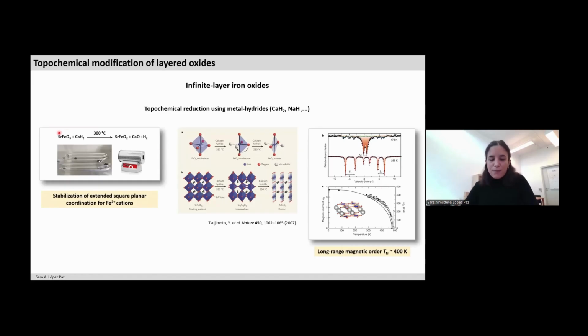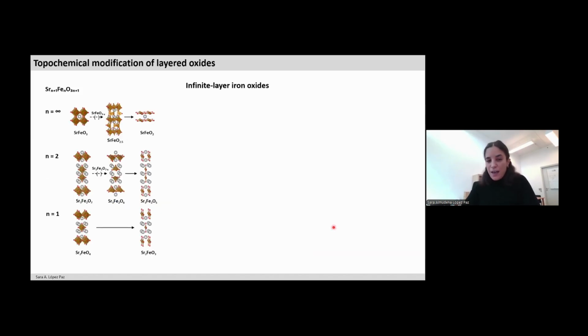They had a beautiful example of how you could reduce an iron perovskite by using calcium hydride at very low temperatures. I know this is not low for many chemists, but in this context, it is actually pretty low. And in this way, they could stabilize infinite layers of iron oxide which were still magnetic with pretty high critical temperatures. And as at the time iron was certainly my favorite element, I definitely wanted to dig further into this method and try to design more targeted low-dimensional iron oxides.